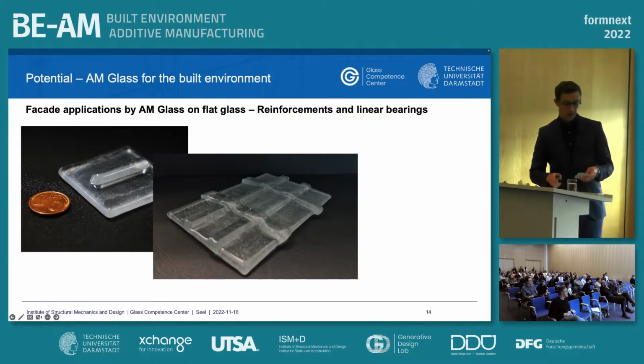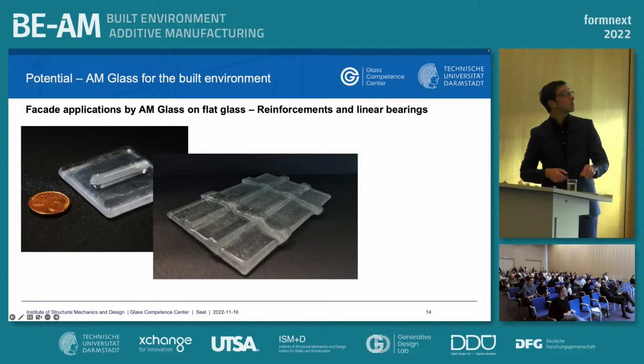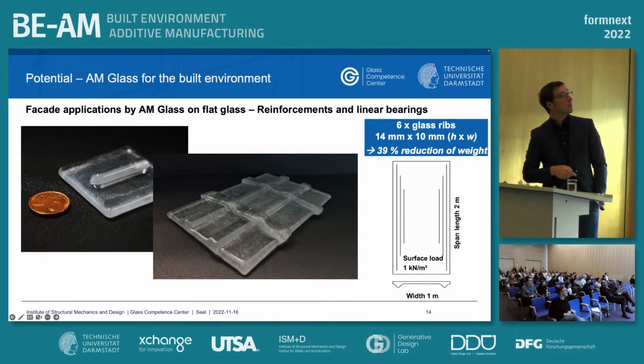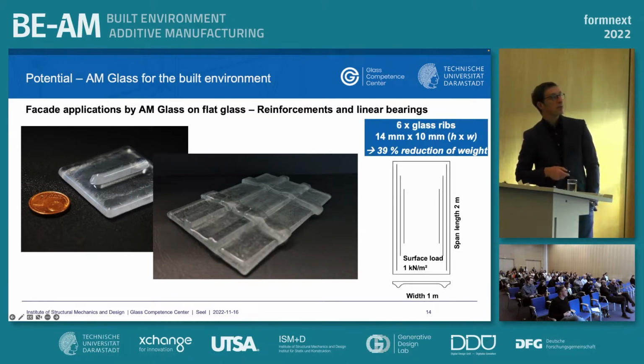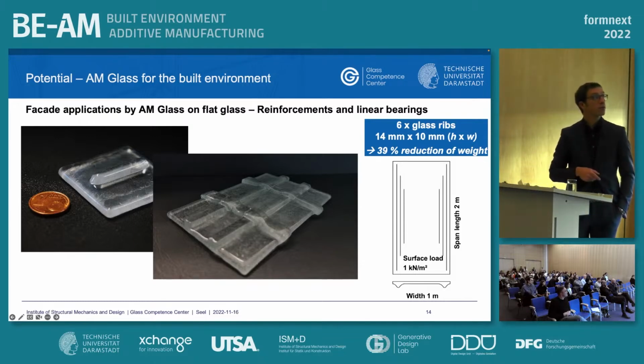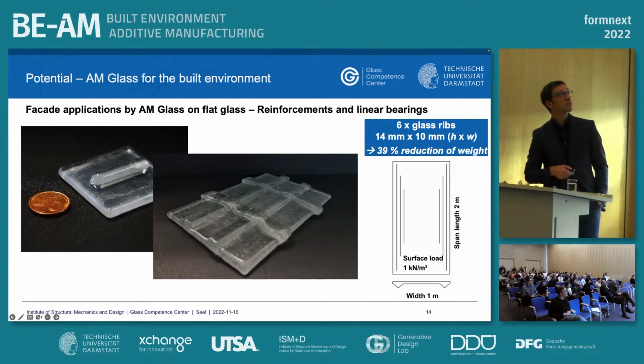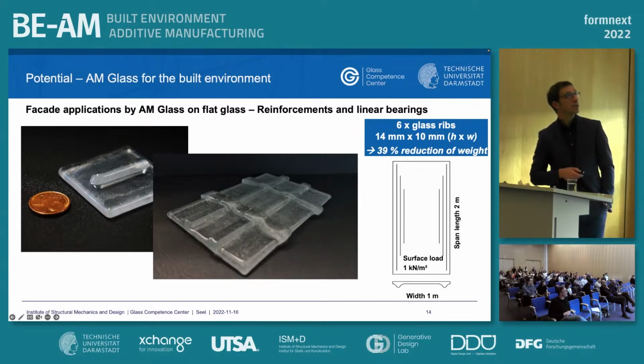What we created is a feasibility study. We bring some ribs on it to stiffen it, and so we can, for example, reduce the weight of such a sample. If we have a span length of 2 meters of such a glass plate and a surface load, with a width of 1 meter, we need 12 millimeter or more for the deflection criterion. If we put 6 ribs in the dimensions of 14 by 10 millimeter on 6 millimeter thick glass, we can reduce the weight by more or less 40%. And if we increase these values, we can reduce more.